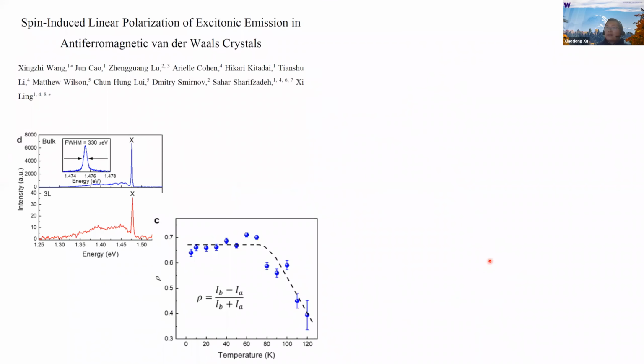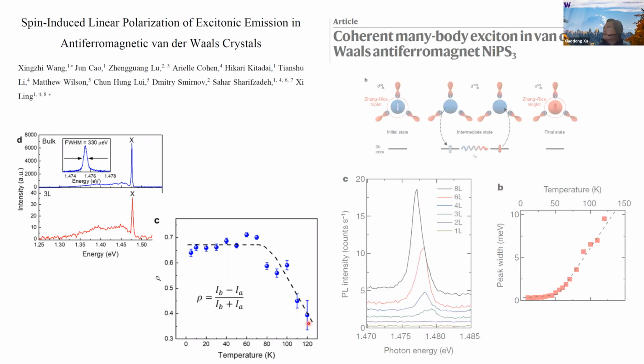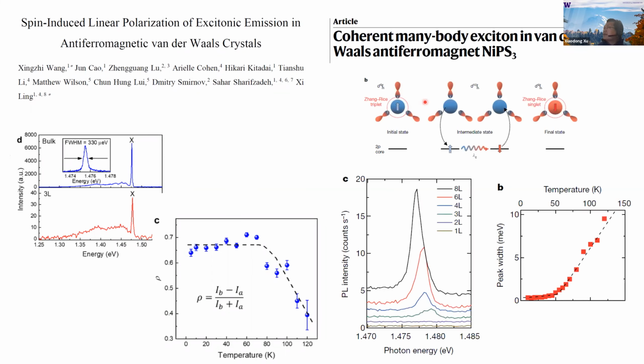We're not the only ones to observe this phenomenon. There's a work from Boston College. They also observe very narrow luminescence from nickel phosphorus trisulfide. The data is consistent with ours, which is really good. They also observe the degree of linear polarization drops as a function of temperature, all consistent.